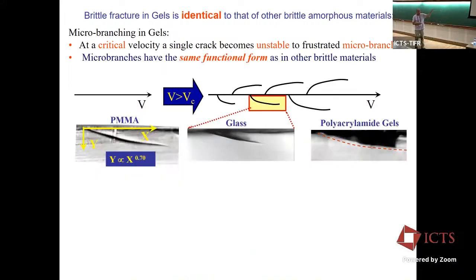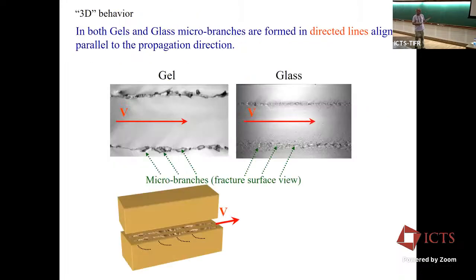Okay, but the structure that they create is identical. And even, this is now a picture, again, of the fracture surfaces that were created here. This is in gels, and this is in glass. You find that these microbranches, this is the top part of the microbranch, and it goes into the material, but you can't see it here. They actually are very localized in the z direction, in the direction that's normal to the propagation direction, and they look the same in glass as well.